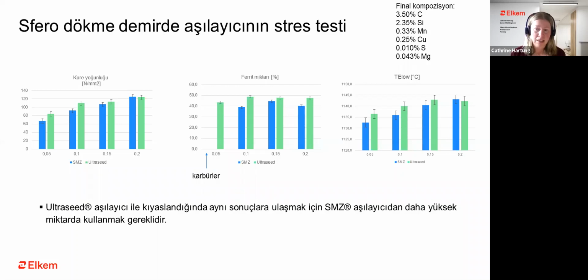And as can be seen here, the Ultraseed is providing a higher nodule density at a lower addition than for SMZ. So the overall nodule density is low because, as I said, this is a tough iron. We have made it tough. We would probably have to have a higher inoculation addition, but we can still see the difference between the inoculants from 0.05 and 0.1, 0.15. You have to be up to 0.2 weight percent of the SMZ to come close to the Ultraseed in nodule density. Similarly, on the ferrite content, for the lowest addition of SMZ, we have carbides in the structure, while we don't have carbides at all with the Ultraseed. And we have a consistently higher ferrite amount with Ultraseed.